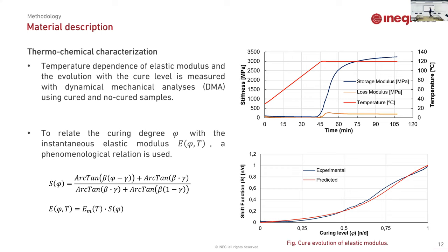But there are more things needed. Even if I already know how the material cures, I also need to know how the elastic properties of the composite or the resin evolve with temperature and with the degree of cure, because the elastic modulus of the material is not the same at room temperature as, for example, at 100, 120 or 150 degrees. The temperature influences the elastic modulus, but I also need to know how it evolves with the degree of cure.